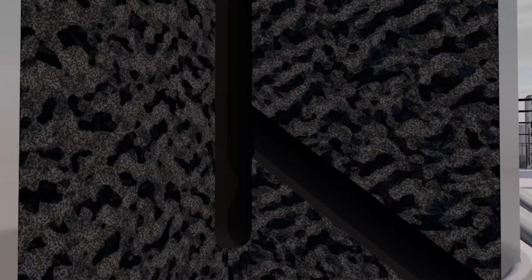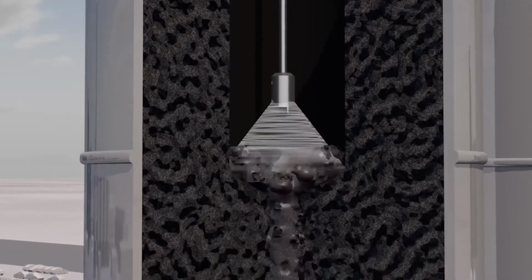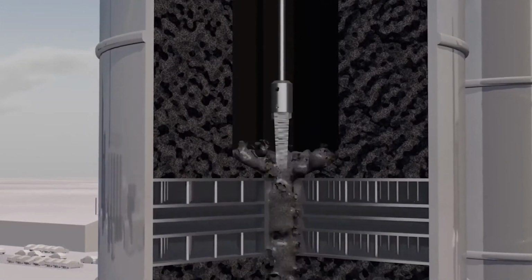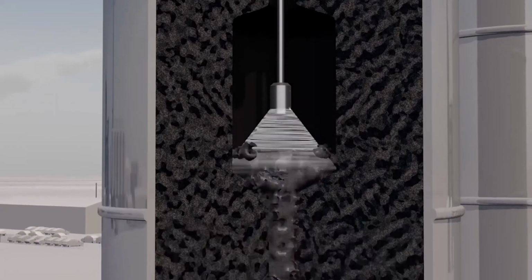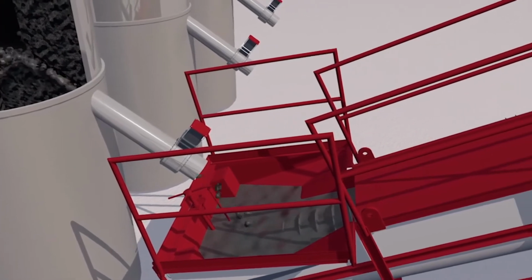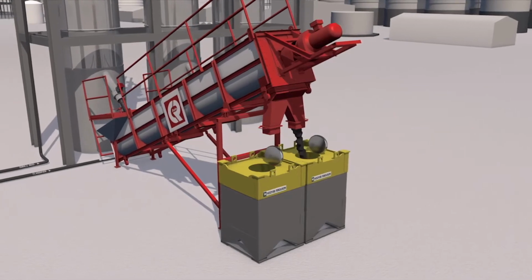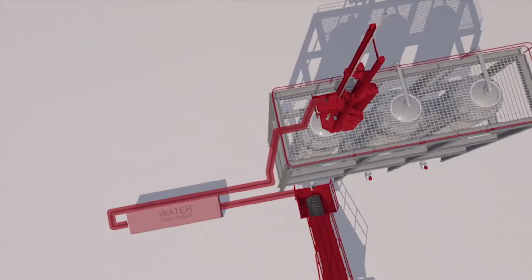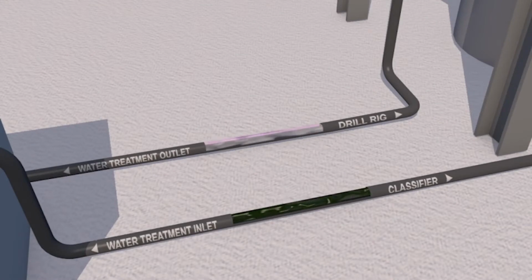Once a clear path is achieved, different drilling nozzles are used to remove the remainder of the spent catalyst, which is flushed out from the bottom dump nozzle. In certain multi-bed reactor designs, we can drill straight through the interbed plate between the top and bottom beds, allowing all of the spent catalyst from both beds to be discharged through the bottom dump nozzle in a single step. The spent catalyst exiting the dump nozzle feeds into a spiral classifier, which drains the water from the spent catalyst before it drops into UN-approved containers. The water is separated, cleaned and treated in a closed-loop system prior to being reused.